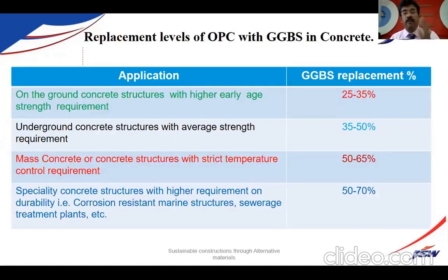Replacement percentage can vary based on the applications. For our regular concrete application, we can use 25 to 35%. Underground structures up to 50%. Mass concreting 50 to 65%. Marine structures, where severe environmental conditions, freeze-thaw reactions and corrosion resistance are concerns, we can go up to 70%. Globally, this product is being used up to 70%.